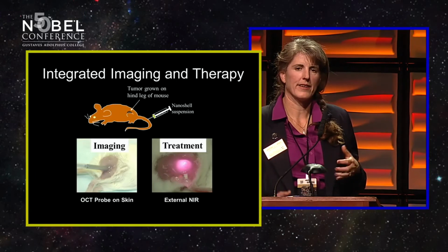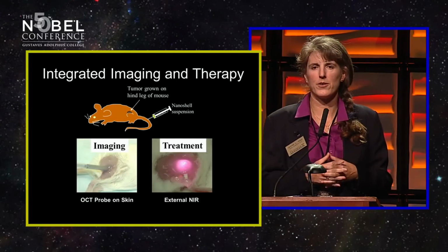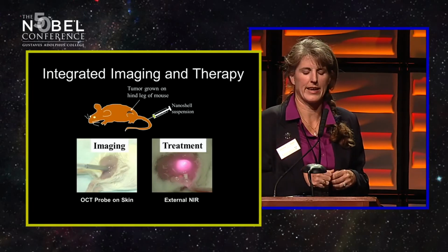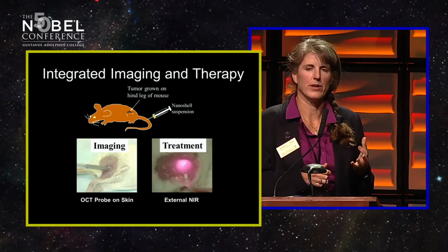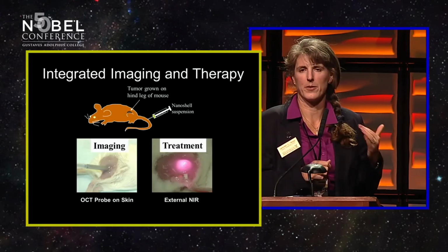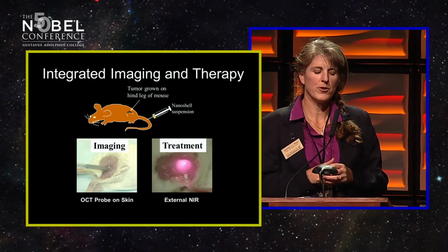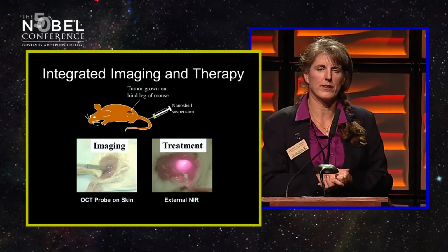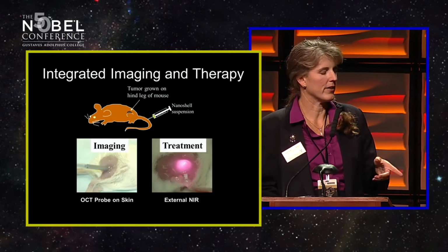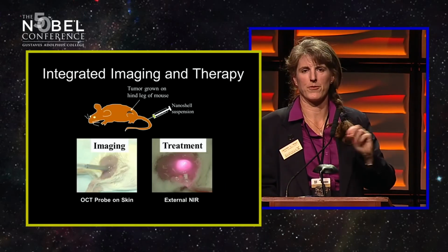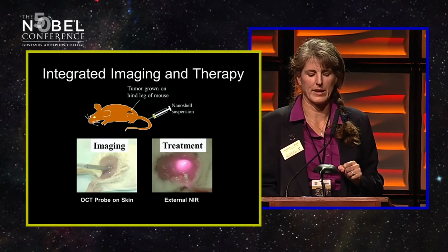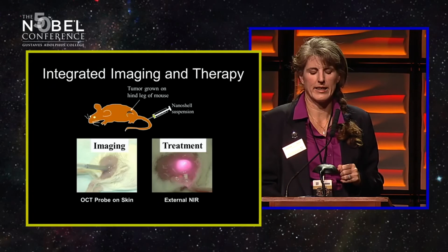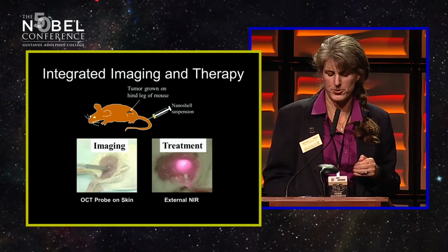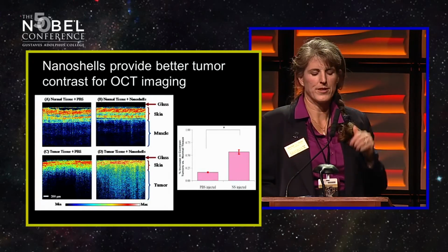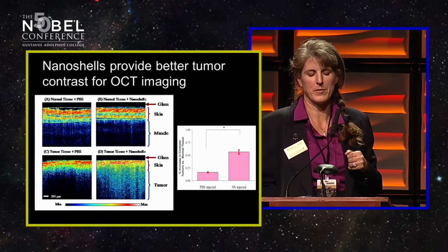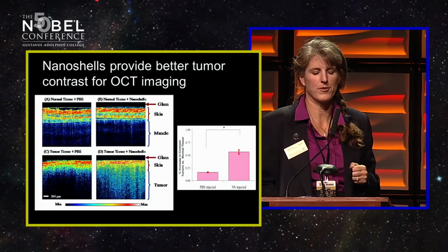So in designing a system for integrated imaging and therapy, we had particles that we designed to be 50% absorbing and 50% scattering so that we could hopefully accomplish both goals. We injected them into the mouse with a tumor, allowed them to accumulate there, and then we first did imaging where we used something called optical coherence tomography. And on the bottom left, you can see we have a fiber optic probe that's just running along the skin of the animal and developing the image. And then we come back with higher intensity light to generate heating sufficient for treatment. And so these are what OCT images look like. They're somewhat similar to a B-mode ultrasound image, and you're looking at basically slices through the tissue.